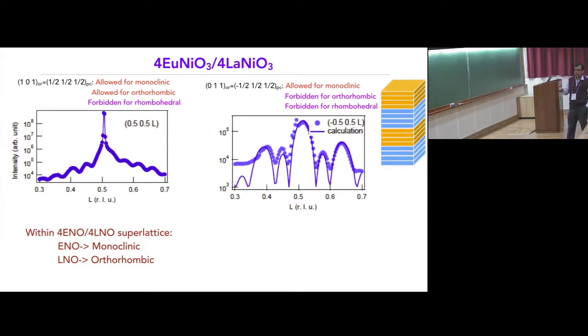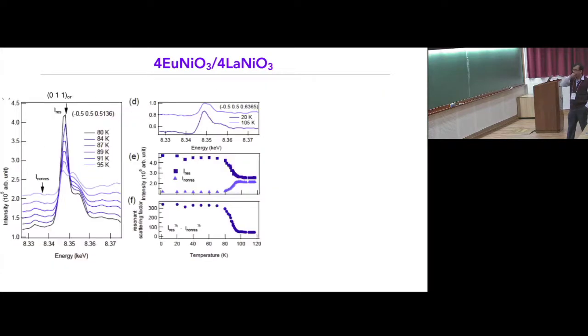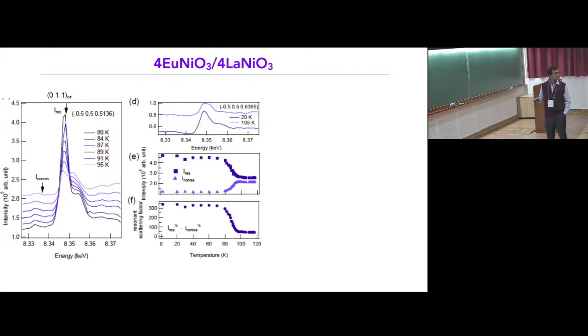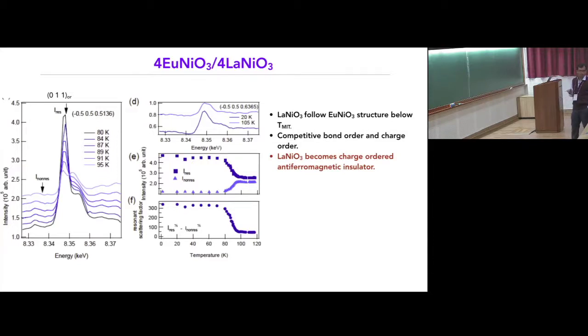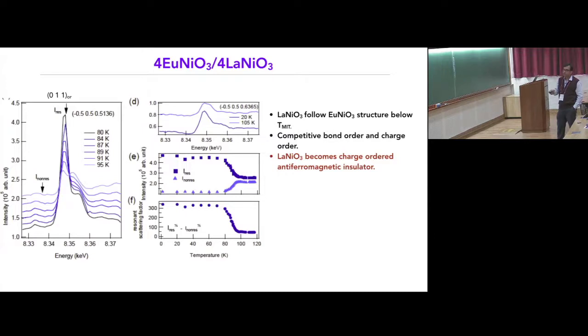For this system we performed resonant X-ray scattering and found something different. Plotting the resonance intensity as a function of temperature, it actually decreases across the metal-insulator transition. But the off-resonance intensity — a signature of bond/structure ordering — decreases below the metal-insulator transition as well. This system is a rare example where bond disproportionation and charge disproportionation are actually competing with each other, not cooperating. There are currently no other examples of such a phase. This is a new phase of matter arising purely because of structural competition at the interface — no charge transfer, just pure structure causing this very unusual phase.